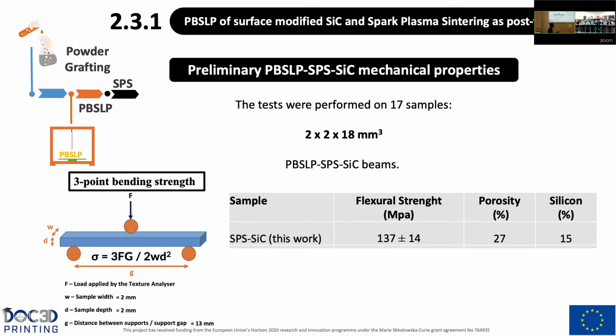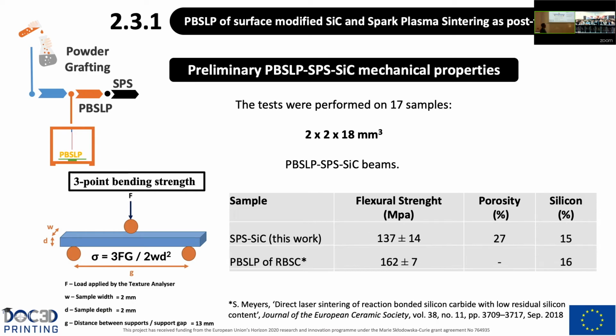Remember, with a porosity of 27% and a silicon content of 15%. If we compare this value with the last strategies, the one that we were explaining in the first slide, the additive manufacturing by laser sintering of reactive silicon carbide, we obtain a similar value, despite the fact they don't have any porosity. They say they are obtaining full density values with a similar content. So probably by decreasing this porosity, we could be closer or even reach a better flexural strength.